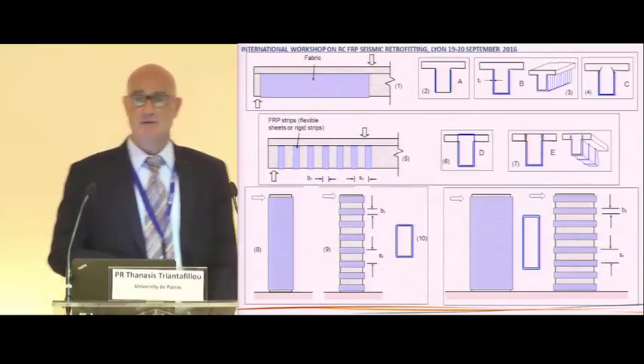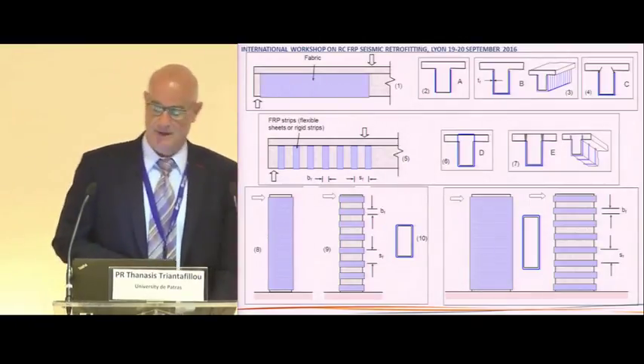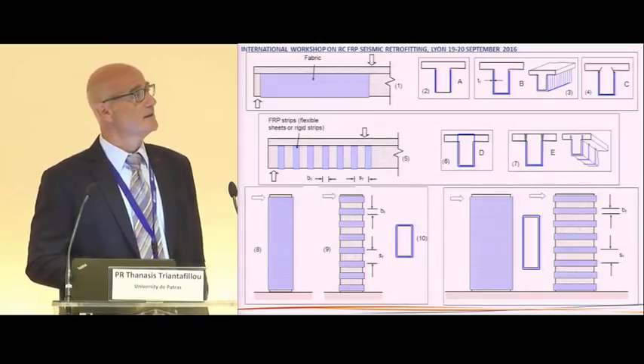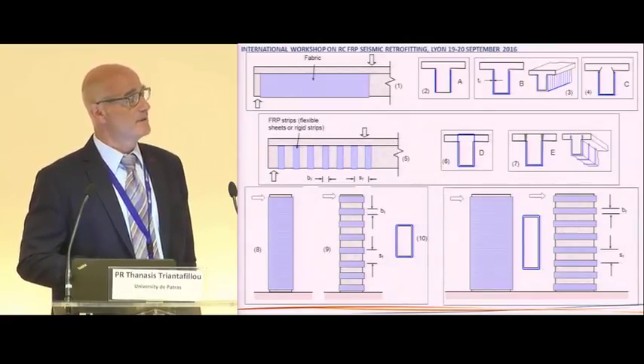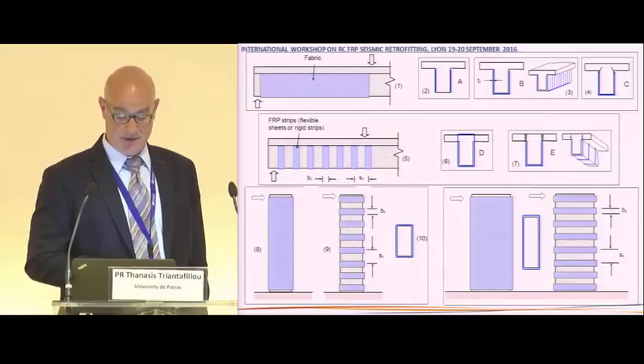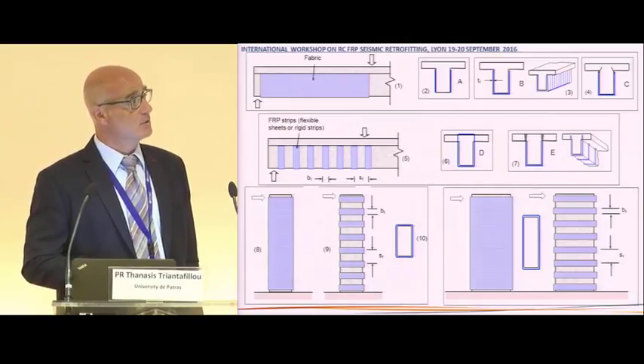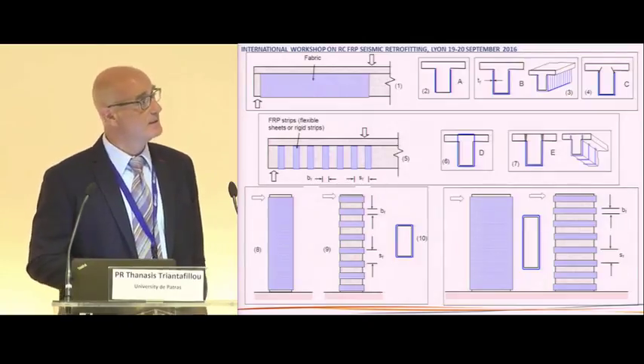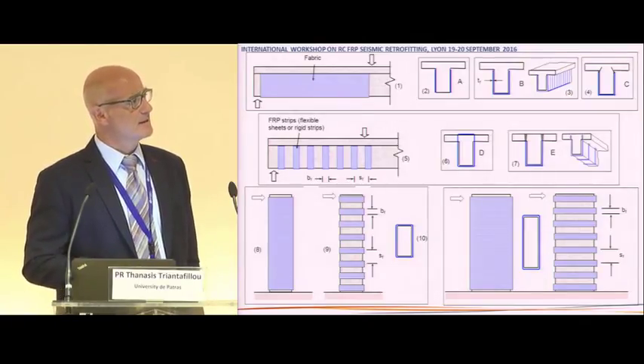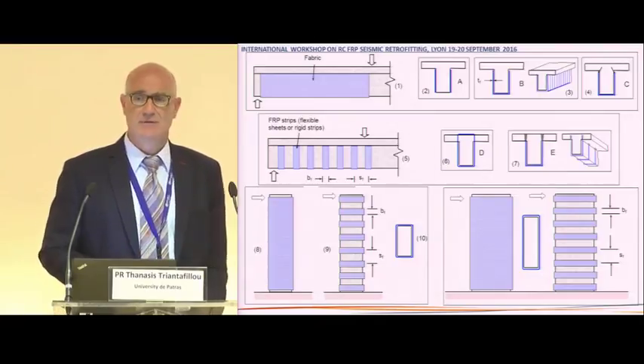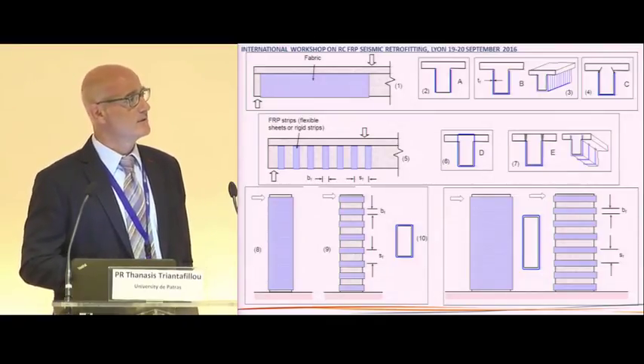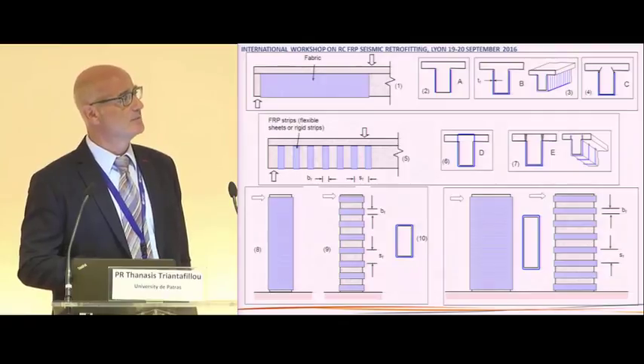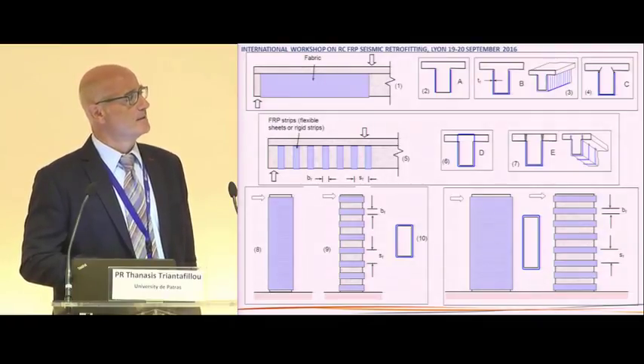These are typical configurations of FRPs to do shear strengthening. In the case of T-beams, we have many options. Normally we do this one. We use three-sided jacketing with or without anchors. This is a two-sided jacketing, which I would avoid. We have no reason to do that. It's not effective at all. It will debond prematurely. We can simply continue the jacket all around in the web.